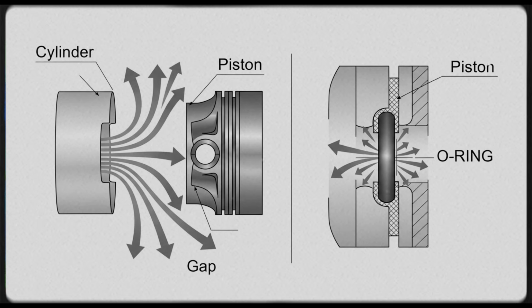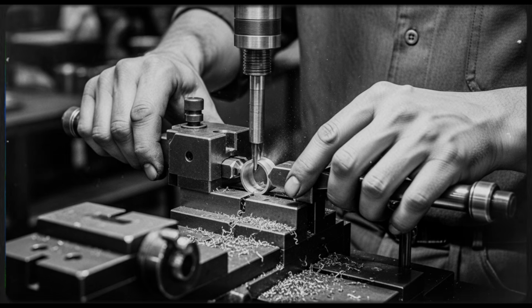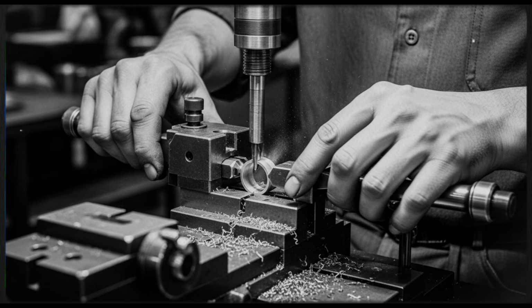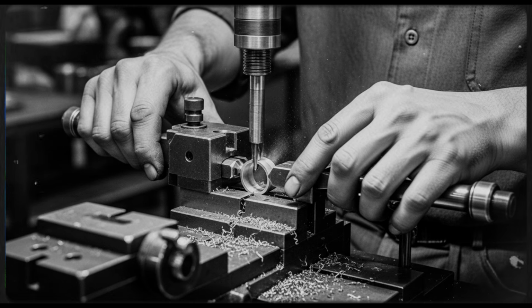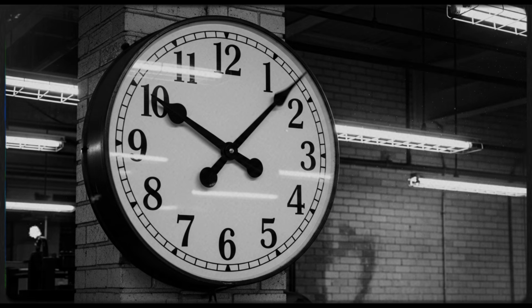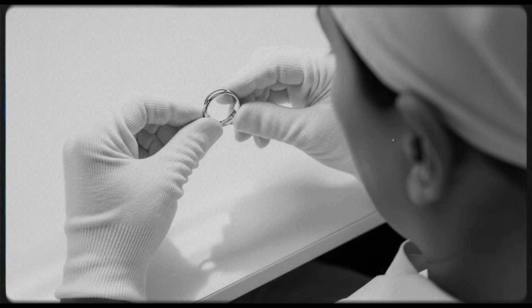After heat treatment, the rings moved to the grinding stations. They had to be ground to incredibly precise dimensions. The outer diameter needed to match the cylinder bore to within 0.002 of an inch. The ring's thickness had to be perfectly uniform around its entire circumference, as any slight variation would lead to uneven wear. The grinding wheels themselves were impregnated with diamonds and wore out after just a few hundred rings. At $50 per wheel, the factory was burning through 10 of them every single day.